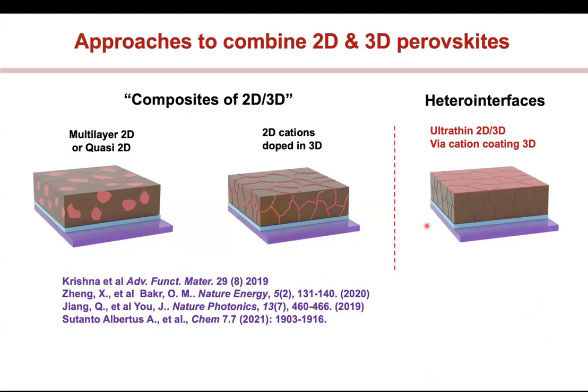And so there have been multiple schemes of doing this. People have done different approaches to this. These are the common ones, where they take these 2D salts and mix them in a 3D film, and you form these islands of 2D perovskite with different band gaps, and they call this quasi 2D. Or sometimes they'll take cations that make the 2D perovskite and use them as an additive in a 3D, and you get something which looks like this, where your 2D perovskites are at the grain boundaries of your bulk perovskites.